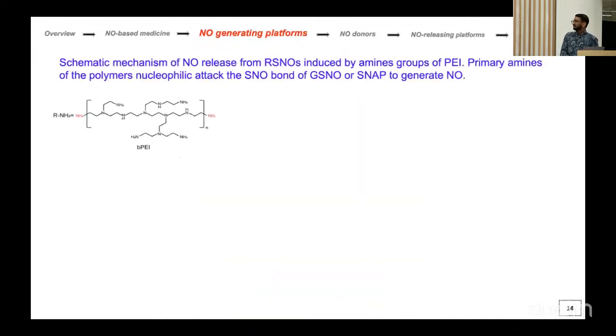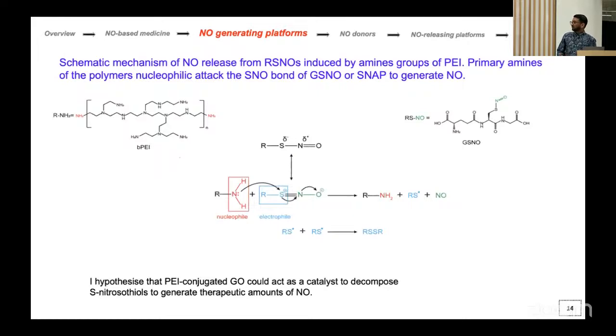So what's the mechanism? This is a branched amine group, which has primary amine groups and also, of course, secondary. And then this is a nitric oxide source called S-nitrosoglutathione, GSNO, in the bloodstream. The amine groups act as a nucleophile, and it attacks the electrophile group of GSNO or RSNO, so that's S-nitrosothiols or S-nitrosoglutathione. And once the nucleophile attacks the electrophile, it splits nitric oxide. So that's the chemistry behind it.